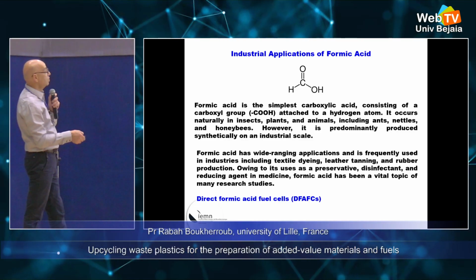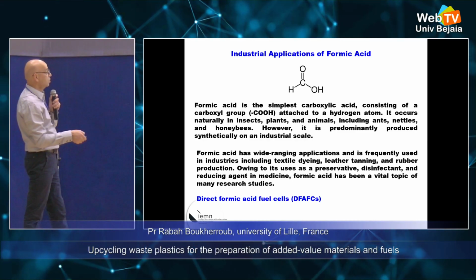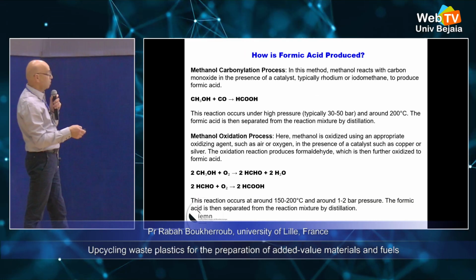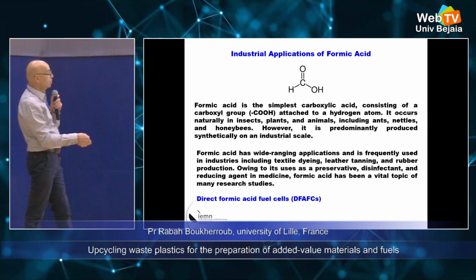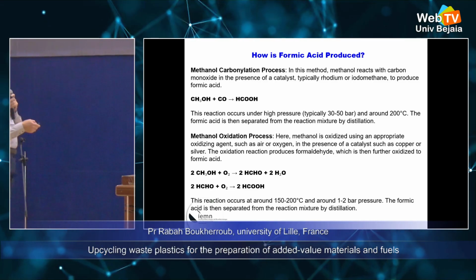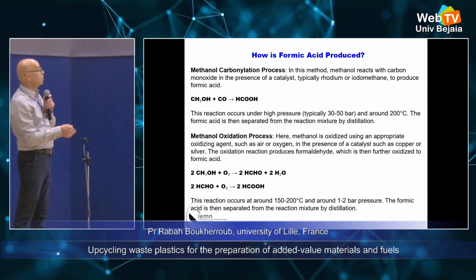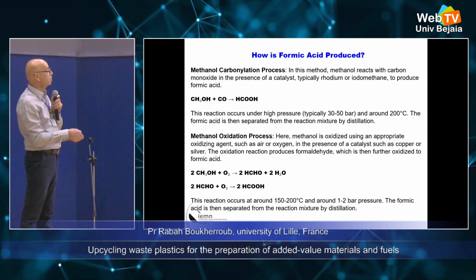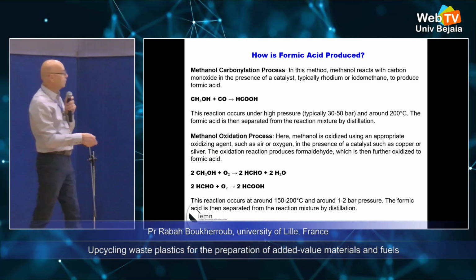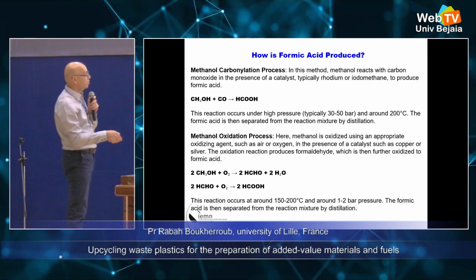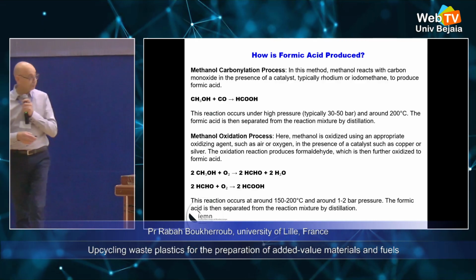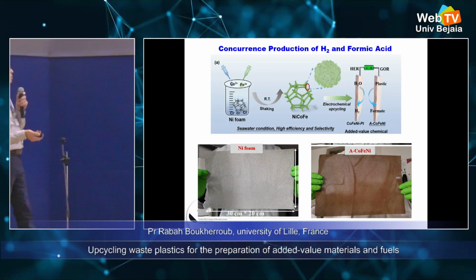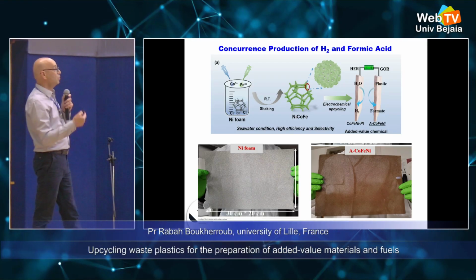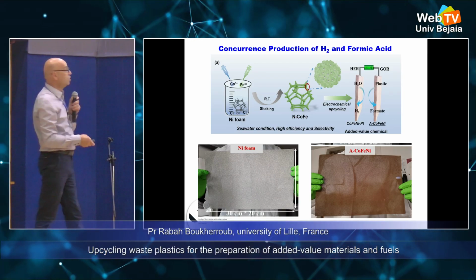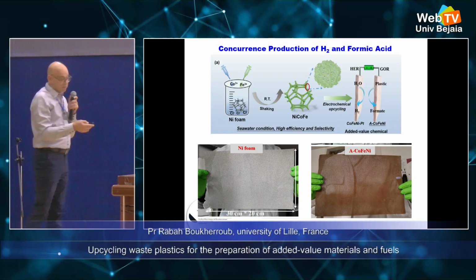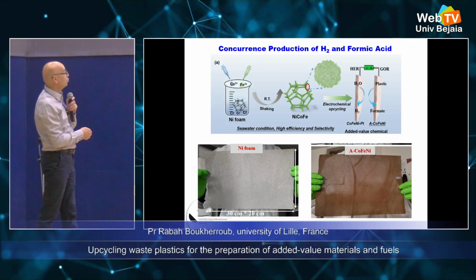Why formic acid? Formic acid is used a lot in industry: textiles, leather, and rubber production, but also for energy because you have what you call direct formic acid fuel cells. Formic acid is produced chemically at high temperature and high pressure using methanol or carbon monoxide, or oxidation of methanol or formaldehyde, often at 150 to 200 degrees C and 1 to 2 bar pressure. Producing it electrochemically will occur at room temperature, and because it comes from ethylene glycol that originates from waste plastic, I think it's a very nice approach.